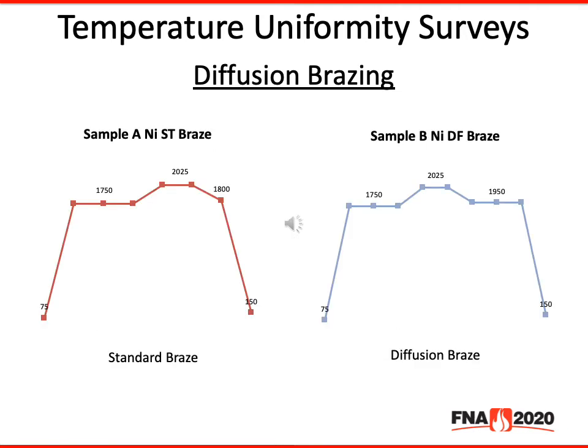There are two braze cycles shown here. On the left is a standard braze cycle. On the right is a diffusion braze cycle. You can see that the temperature is held after the braze at 1950, whereas the standard braze on the left, it is not. In this case, this 1950 hold is what makes it a diffusion braze cycle.